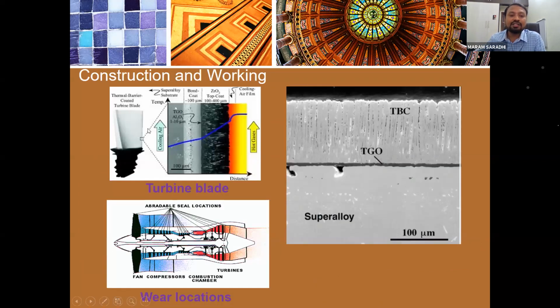If you see, it is made up of a super alloy. On the top, you coat a bond coat. Some of the compositions of the bond coat. On the top, you coat a zirconia, the black one here, the zirconia thermal barrier coating. So this top coat, the thermal barrier coating, is only exposed to the temperature, not the blade composition.